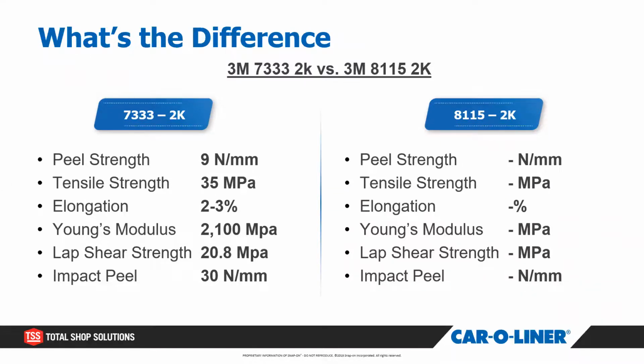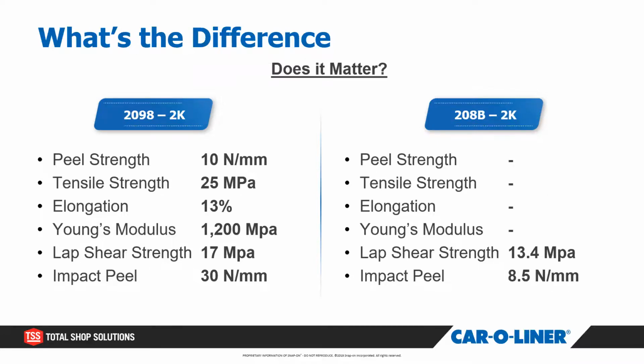When you look at the structural adhesive versus the panel bond adhesive, I reached out to Doug Craig at Fuser, and unfortunately they didn't have the peel strength and tensile strength tests done for the 208B, but just look at the impact peel difference. When you look at the lap shear strength, the 2K panel bond versus the structural adhesive, they both have very good tensile strength. The adhesive sticks very well. So you can see the lap shear strength is very, very similar to each other.